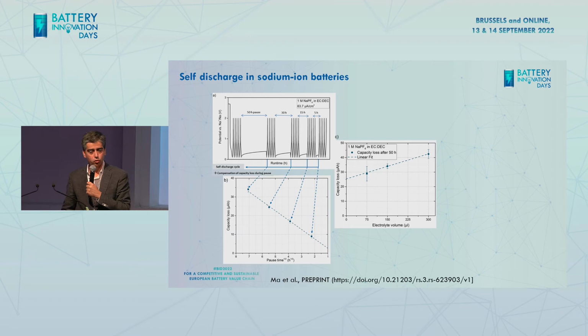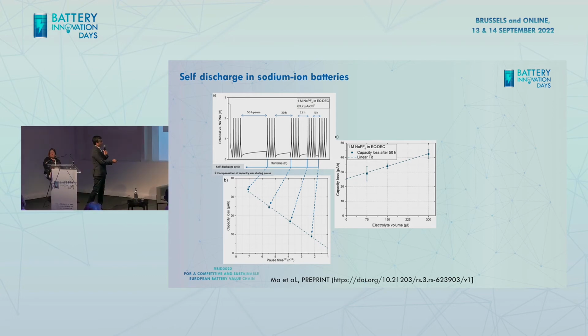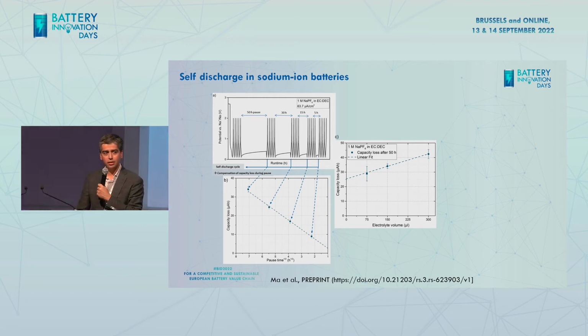It is a problem for lithium-ion batteries, of course, any kind of batteries with this type of setup, but this has been addressed a lot in industry for lithium-ion batteries, but we need to have a better understanding of this for sodium-ion batteries. There's another interesting message from here that if you look at the figure on the right and the onset to the y-axis, you can see that actually the capacity loss is not zero when you move to volume of 0. This is interesting because then this tells us that this SEI dissolution is not the only issue that we have in sodium-ion batteries.